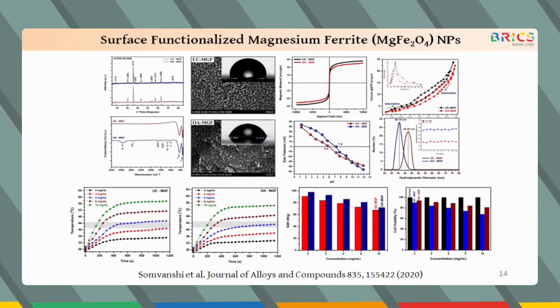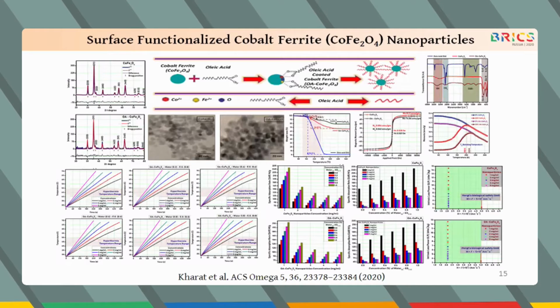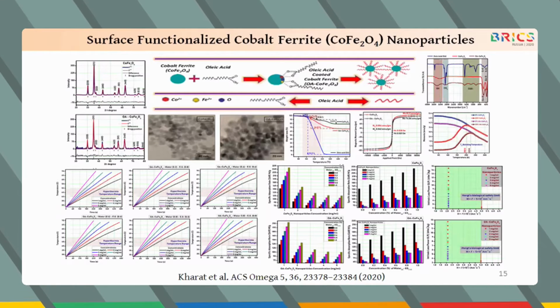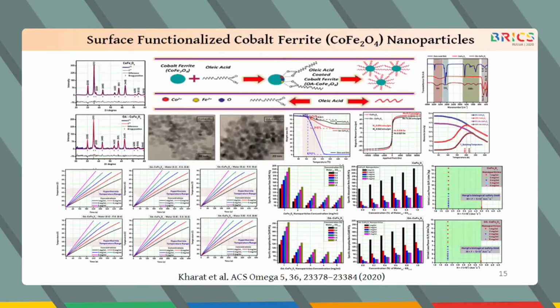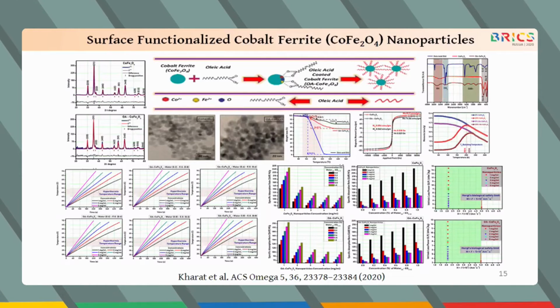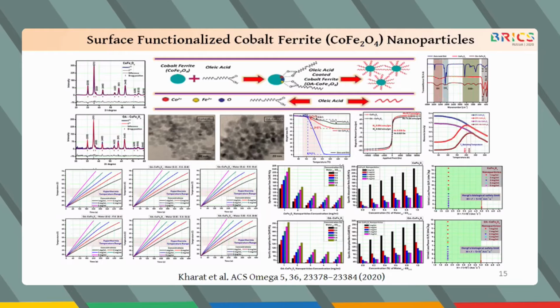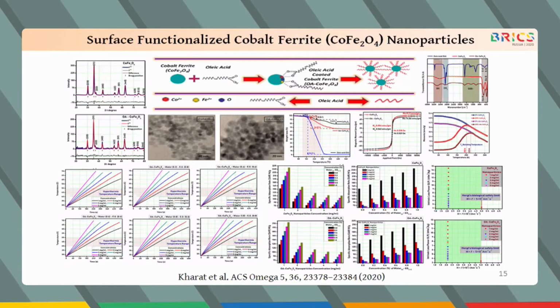So in addition to this, we also studied the effect of carrier fluid on the heating performance. We have studied cobalt ferrite nanoparticles dispersed in water and ethylene glycol, and in combination of both. We got some interesting results in the case of combinational carrier fluid.